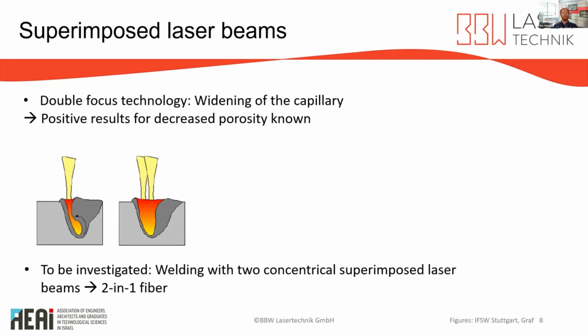Here we see another possible strategy, the usage of a superimposed intensity distribution by different laser spots. The idea of the so-called double focus technology is the widening of the vapor capillary for a better keyhole stability and requires either the splitting of a laser beam or using two different laser beams. Or you just have a laser source which is able to create multiple spots in a very fast time. We would like to add here our own investigations with the 2-in-1 fiber, so the bright line technology, which also superimposes two beams, but in a concentrical way.